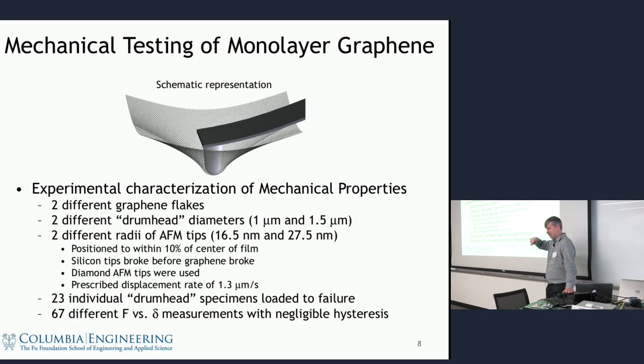And that was actually reflected in the force displacement curve, where you saw weird bumps and things like that. We thought maybe we were banging the tip into the bottom of the hole at the end of the experiment, but we actually finally managed to see that we could break the tip even without breaking the graphene. Right? So graphene is just that strong.